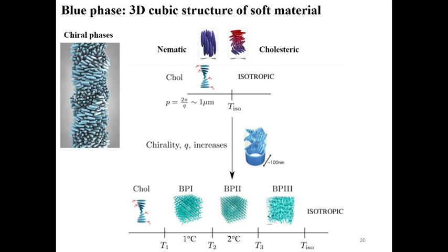For the cholesteric phase, if you look at the schematic shown here, because of the rotation of the molecules, you can control the interference with those cholesteric liquid crystals. And by changing or varying the pitch here, you can control which wavelengths of the incident light will eventually be reflected out. That's why for the cholesteric phase you usually observe very tunable, controllable, different colors.